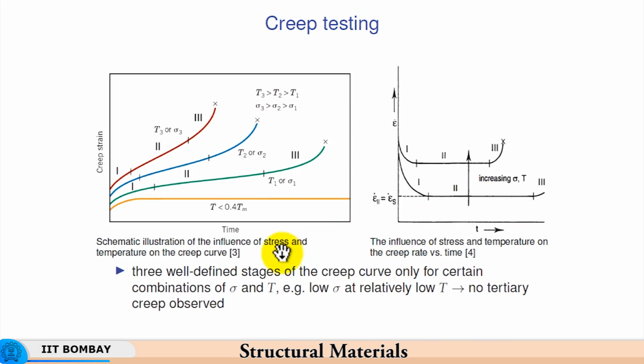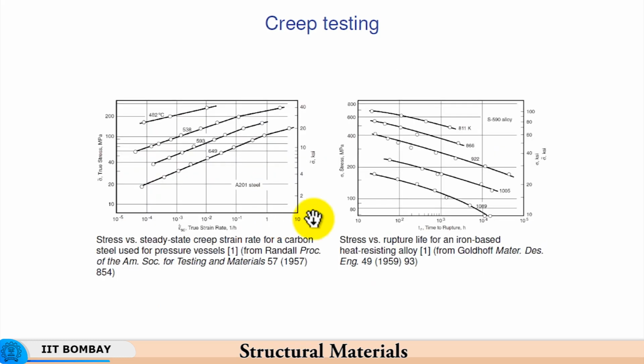As stress and temperature, or both, increase, the creep rate also increases. So, the steady state creep is higher at higher temperatures and higher stresses. Here we see that the rupture life comes down as the stress increases, and also with increase in time. This is again because of the creep damage or the creep strain getting accumulated continuously, and after a certain time it would rupture. Now, you have creep strain rate under steady state. The creep strain rate continues to increase with time, and for a given time the stress which can be withstood diminishes with increase in temperature, because creep will become increasingly faster with an increase in temperature. So, at a smaller temperature the material can withstand higher stress for the same creep strain.